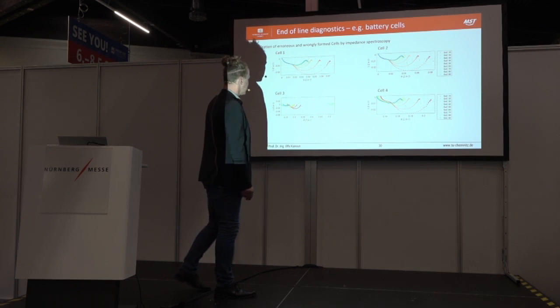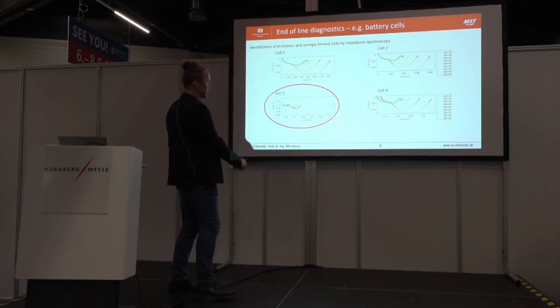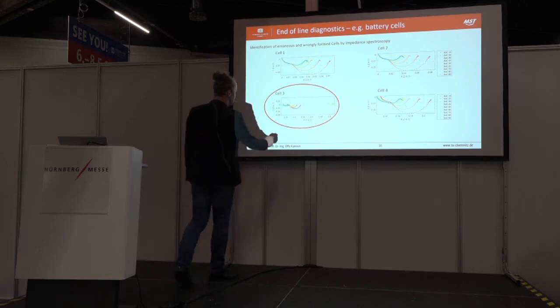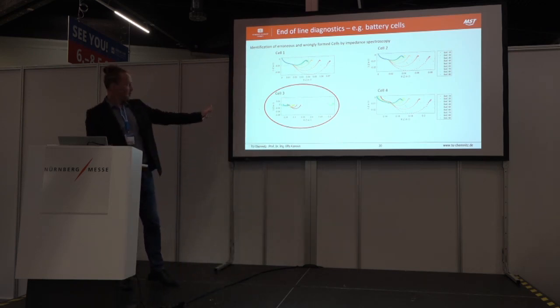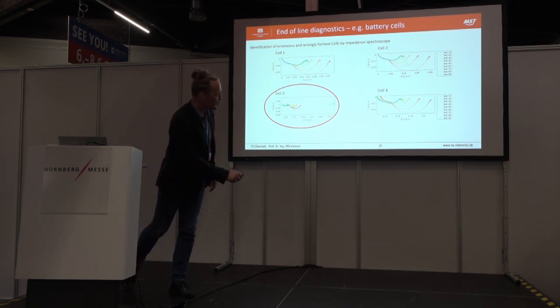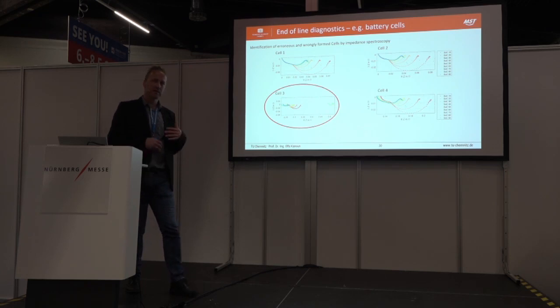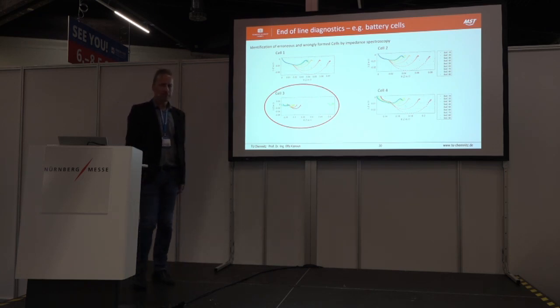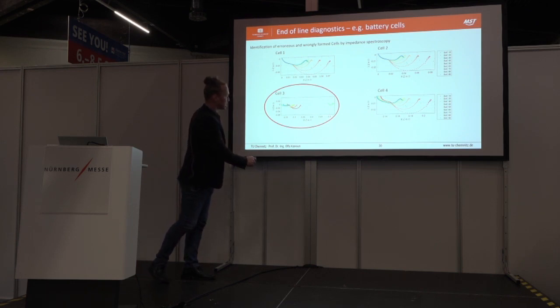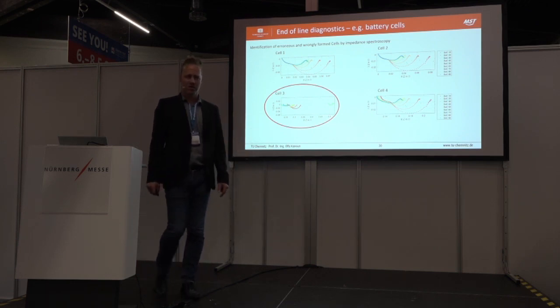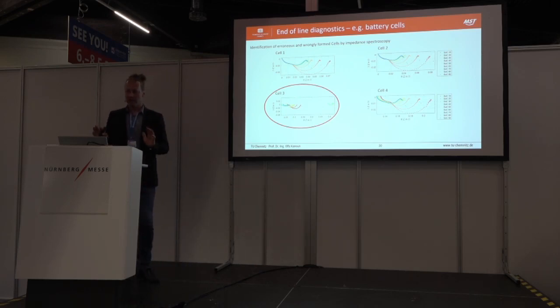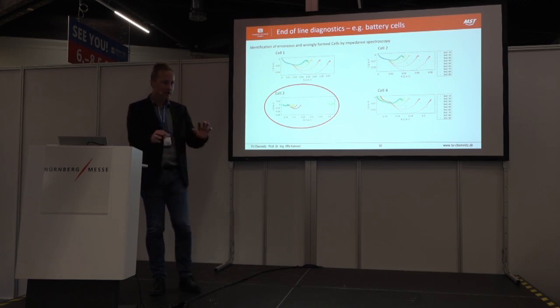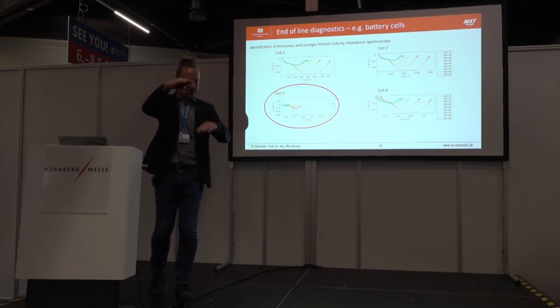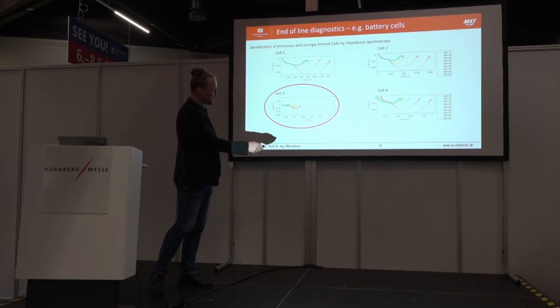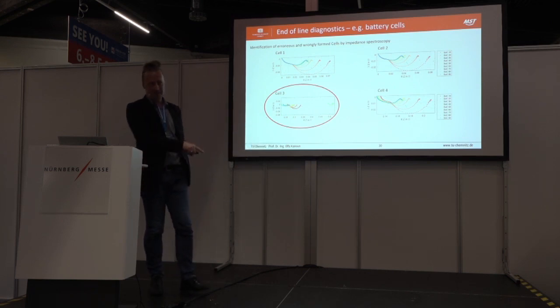So, and what do we face, and why do I put this slide here? You see in cell 3, we had a phenomenon. Exactly at SOC 70%, the impedance spectra run away. So, if you take a look here, 0.5 ohms real part, easy, no point. But you need to understand, 70% SOC will really be used in practice. You know, batteries in practice will be used only in a small range, but 70% is in. So if you have this phenomenon at maybe 20 or 30%, doesn't matter, but 70% will be used.